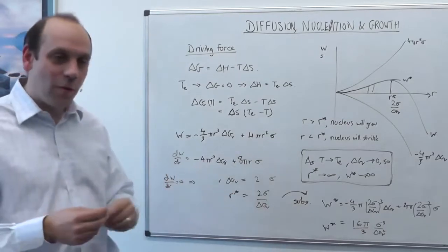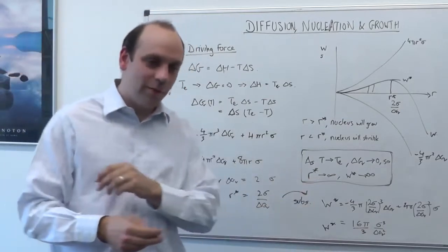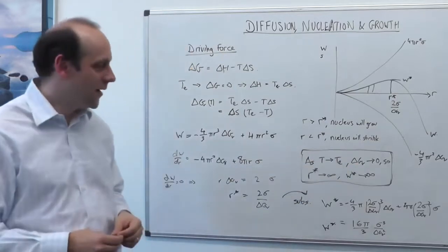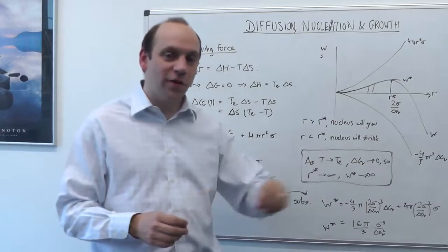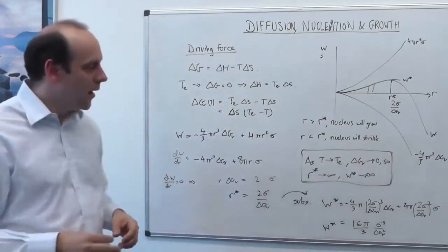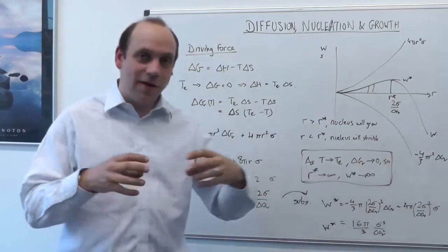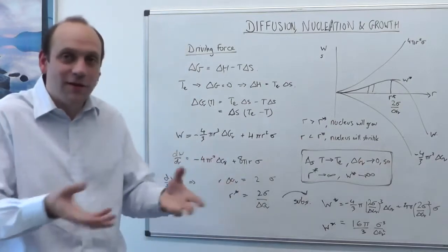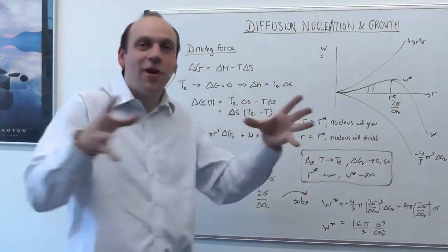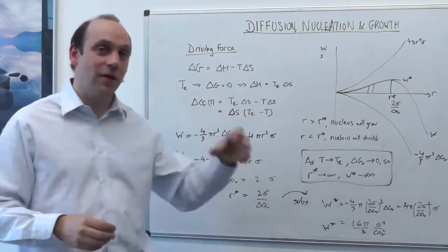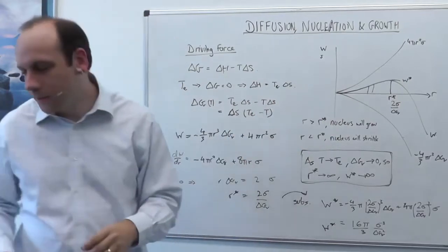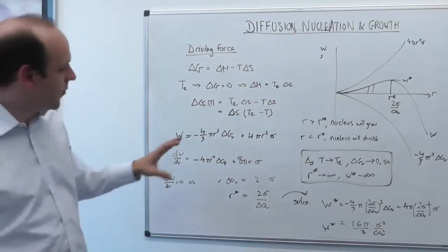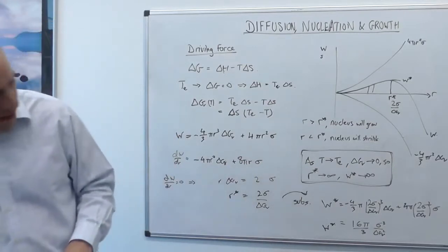Another example is when you're welding aluminium alloys, quite often people will sprinkle scandium, or scandium oxide, into the alloy, which provides nucleation sites. And that results in a much finer grained microstructure in the aluminium weld, because you have more nucleation sites, so you end up with more grains starting to grow when you first form the solid from the liquid. We can keep on going with this. There's one or two last little things to say.